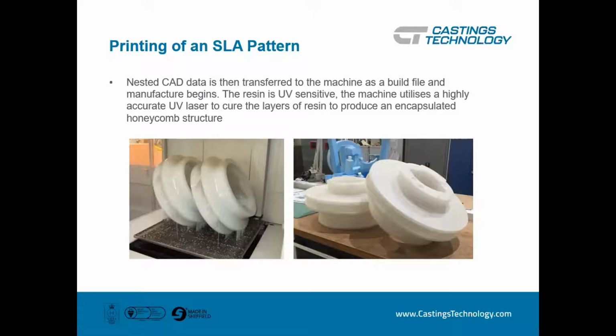And if you don't know, the resin's expensive, so we don't like to use very much of it. But joking apart, what happens is if we create this in a solid resin, put it in a ceramic shell, and then try and fire it to burn it out in an oven, the first thing it will do is expand, and that cracks the shell.